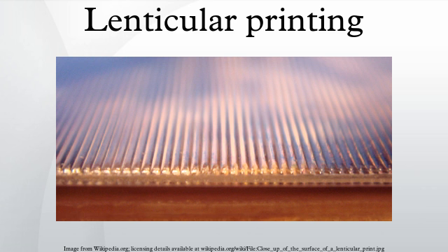Cutting defects. Defects in the way the lenticular lens is cut lead to phase errors between the lens and the image. Two examples, taken from the same production batch. The first image shows a cut which removed about 150 micrometers of the first lens, and which shows irregular cutting of the lenticular lenses. The second image shows a cut which removed about 30 micrometers of the first lens. Defects in cutting such as these lead to a serious phase problem.